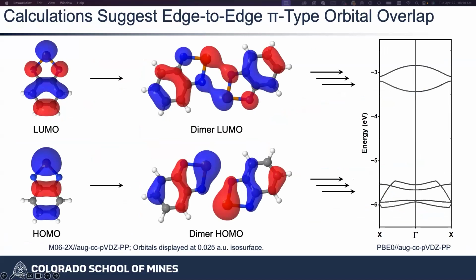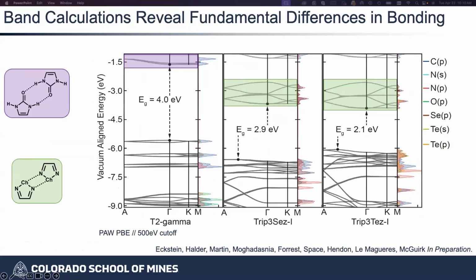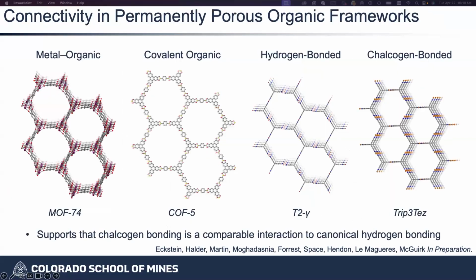And so one of those things that we figured out from an abbreviated calculation is that we're getting 1D band dispersion through those non-covalent interactions, which is a very weird thing. And we can actually show now with those full structures, comparing a hydrogen bonding system to a selenium-based system to a tellurium-based system, that these interactions are leading to semiconducting behavior that we're extremely excited about. So I'll leave it there with saying that what we think we've been able to do, validated through single crystal, powder, and microED, is basically establishing an entire new class of permanently porous materials through these interactions.